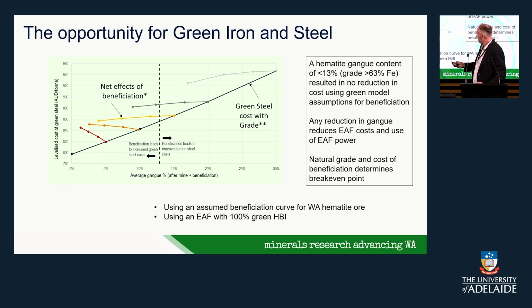So in this case, at 10% gangue, which is actually about silica plus alumina, about 6%, the beneficiation actually doesn't lower the cost of green steel. So this actually equates to current Pilbara grades. It's one of the reasons why, using current beneficiation methods, you actually don't get any benefit in terms of EAF steel making.